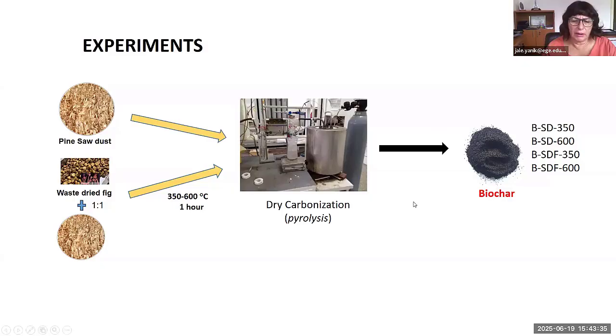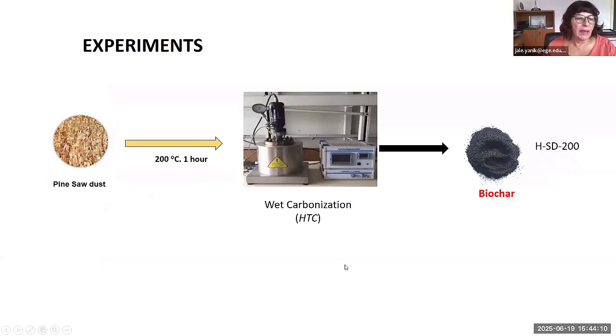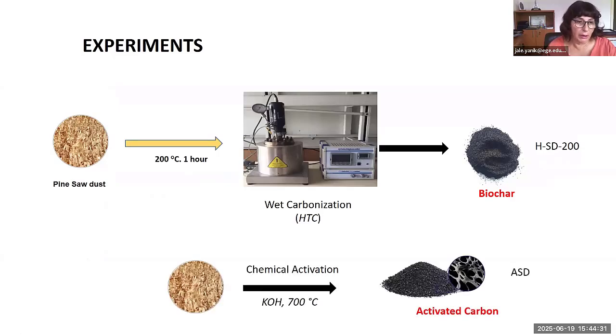We obtained the biochar at different temperatures and with different carbonization methods. In dry carbonization, we use 350 and 600 degrees Celsius as pyrolysis temperature. The obtained biochars are defined in the following order: B, biomass type, and pyrolysis temperature. In the wet carbonization experiments, we used only pine sawdust as biomass feedstock. We also produced the activated carbon because, as you know, activated carbon has more pores and higher surface area than biochar. The activated carbon was produced from sawdust by chemical activation.